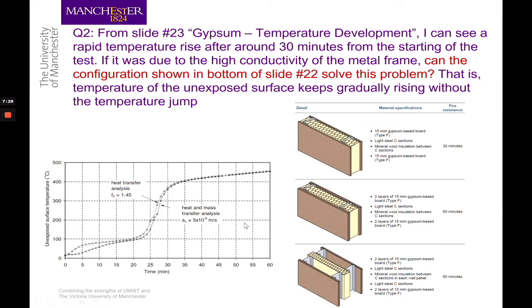So the performance of gypsum in the left-hand side picture, where there is a rapid increase after around 30 minutes, is not because of the use of metal in the system on the right-hand side. It's simply the performance of gypsum. This rapid increase is because of the high rate of heat flux after around 25 minutes of fire exposure, because the fire is at very high temperatures, and also because the water has not been totally driven out of gypsum.